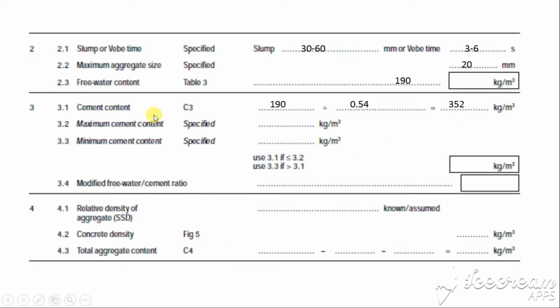Next, refer to the C3 formula. You will calculate the cement content using free water content divided by the 0.54 water cement ratio. You will get 352 kgs per meter cube for the cement content. For the maximum cement content, no need to specify. For the minimum cement content, no need to specify.